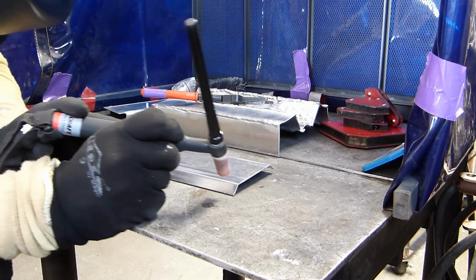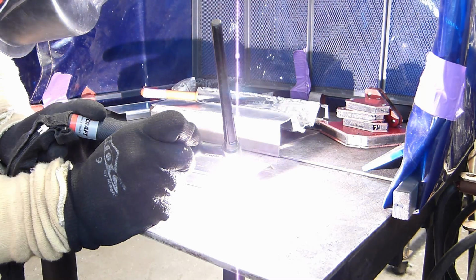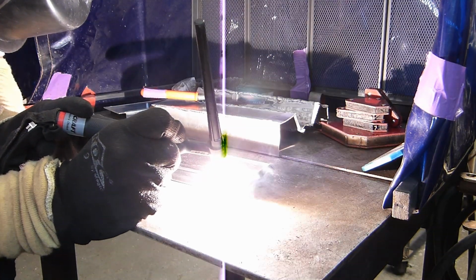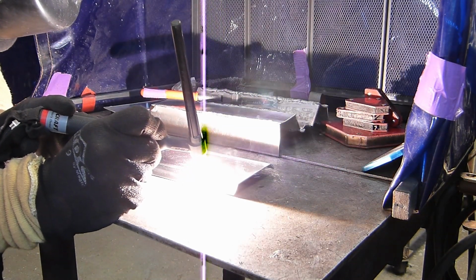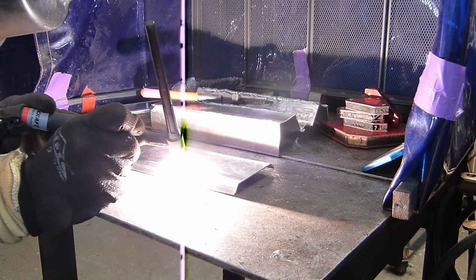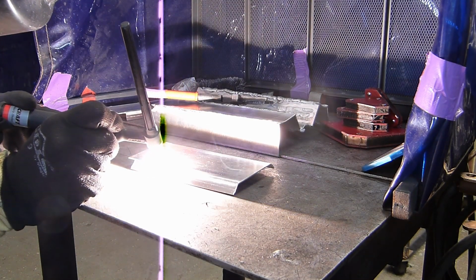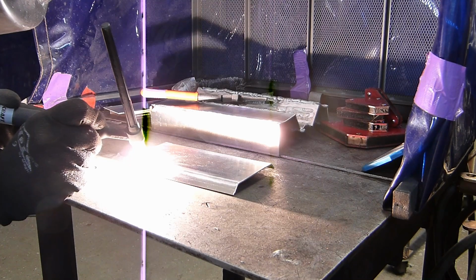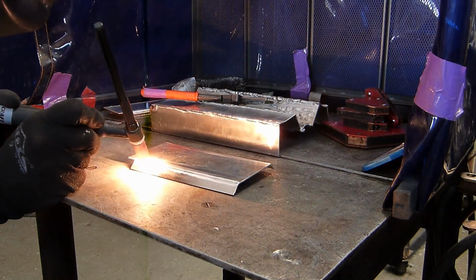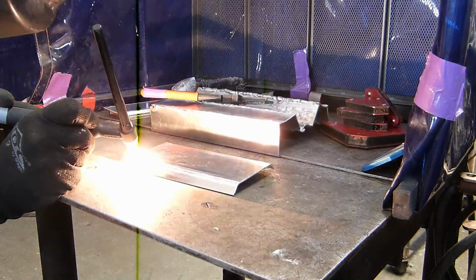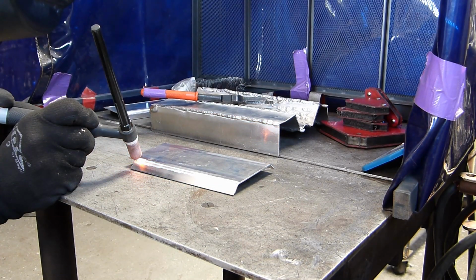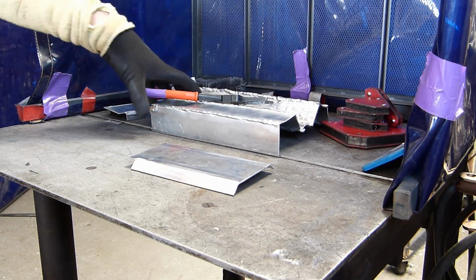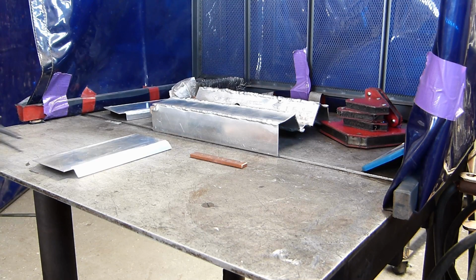So the trick I used was this autogenous welding. I'm not adding filler, but you can see I am quickly pulling up that corner, pulling up that fracture area. So the material is fractured apart, but now I am sort of reflowing those cracks, and those cracks are fixing themselves, you can say.